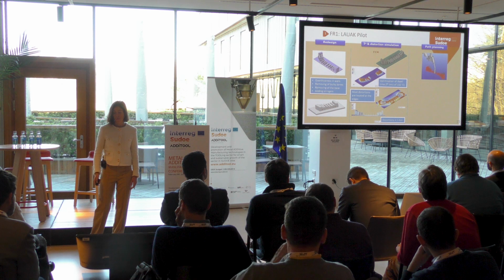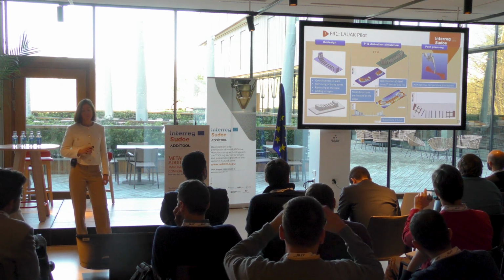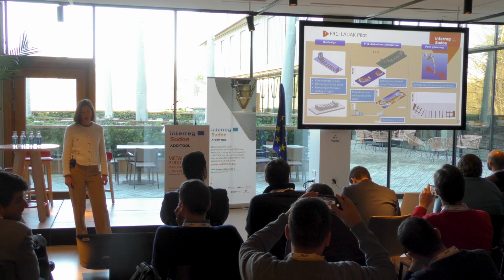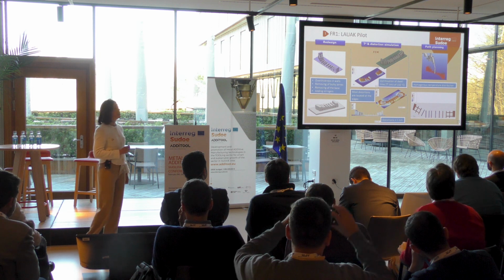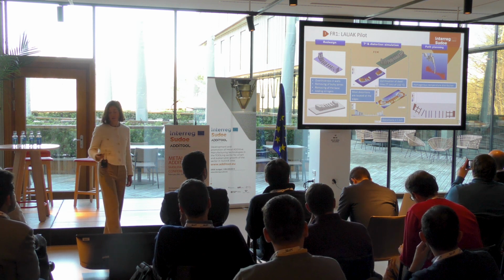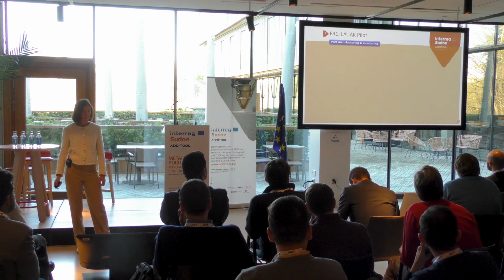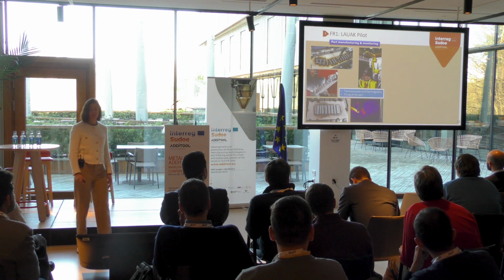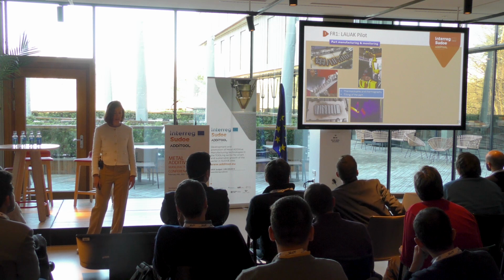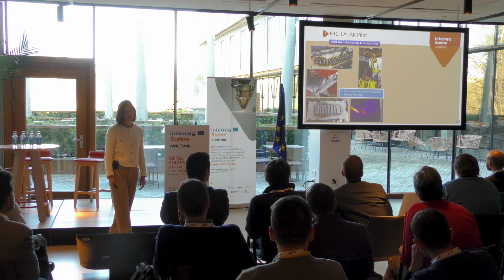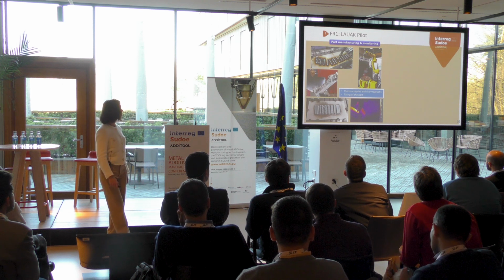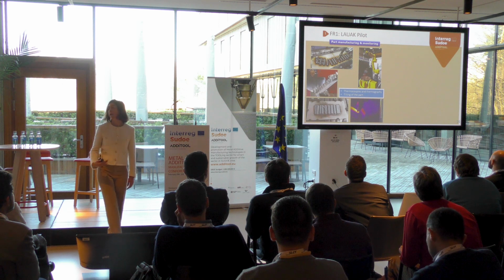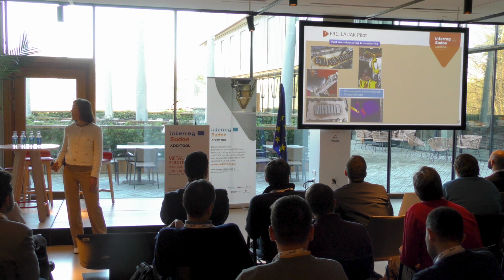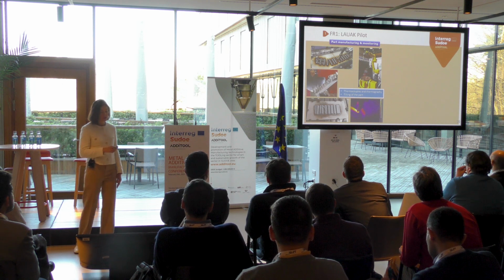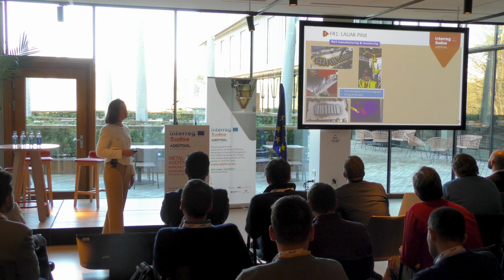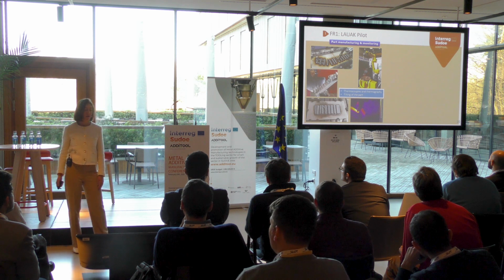Taking all of this previous work into account, we defined the robot path planning and the sequence of the robot in each layer in order to have homogeneous temperature distribution. Then we manufactured the parts with the different technologies, with a robot and laser heads or welding torch. We also applied monitoring, concretely thermal monitoring with thermocouples and thermal cameras. In the case of the use of DED powder laser, the tilting of the part was also a challenge to overcome.